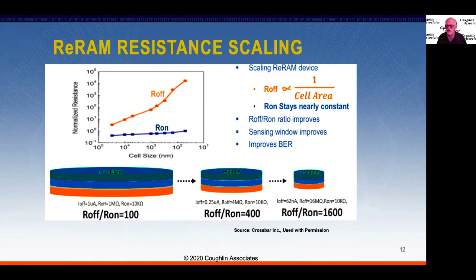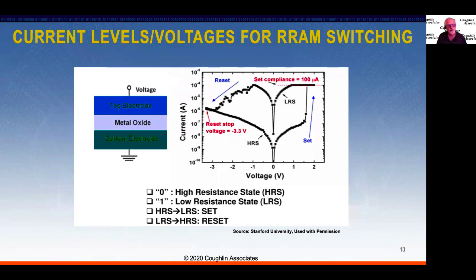Filamentary resistive RAM poses unique manufacturing challenges. The cell resistance has an inherent variability that is proving difficult to manage using today's wafer processing techniques. Additionally, the chalcogenide glasses used in some of these technologies are difficult to integrate into a standard CMOS process. For either metal bridge or oxygen vacancy resistive RAMs, the bit cell consists of a resistive RAM structure deposited above the select device at the back end of line. The cell dimensions are determined by whichever is larger — the resistive RAM or select device. The select device keeps current from leaking into other memory cells, which is a very important function.